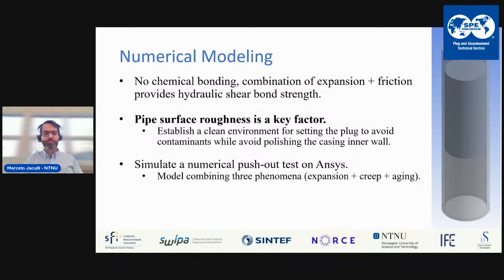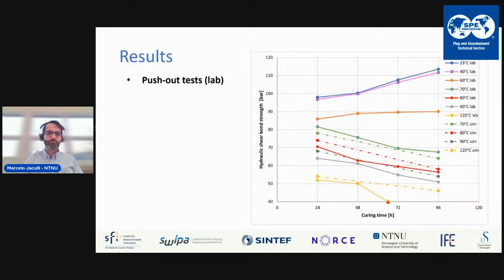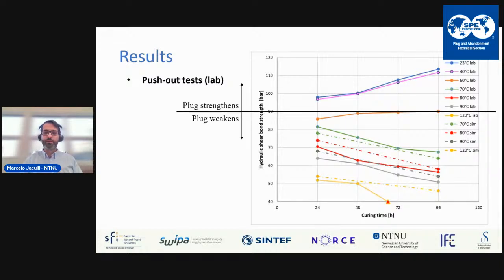We have proposed a model that combines the three phenomena described here. From the lab results, we saw for this particular eutectic bismuth tin alloy that you have a threshold temperature of 60 degrees. So if you think the melting point is 138, you could apply this alloy up to 60 degrees of bottom hole temperature, or if you want to set it as an environmental plug, whatever temperature you have there, probably less than 60 degrees.